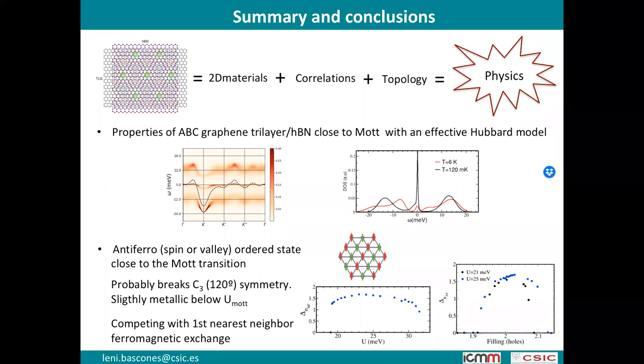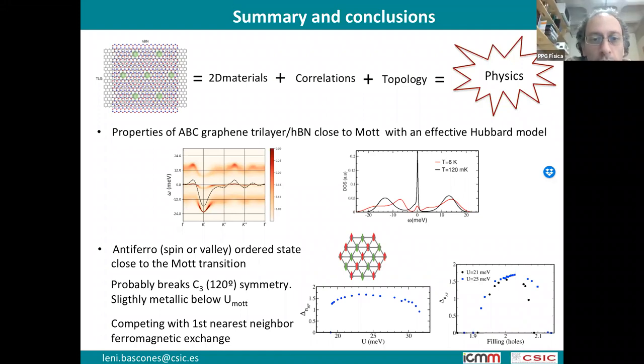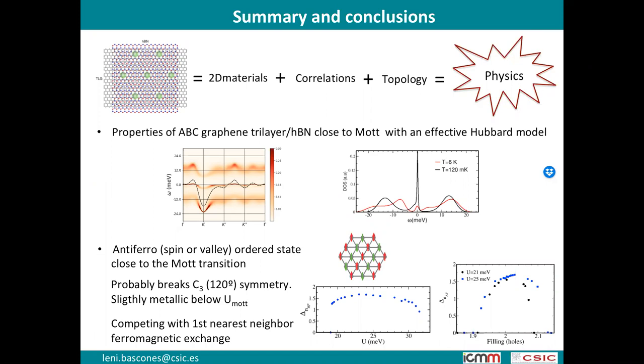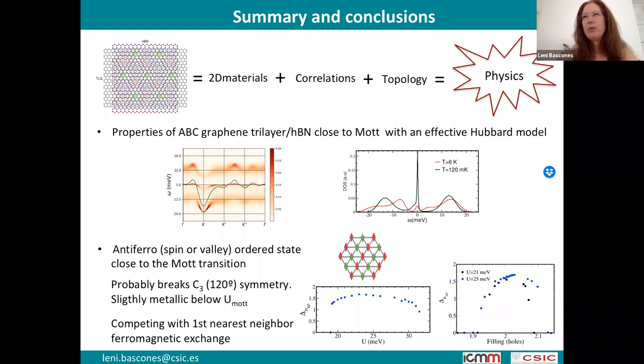My question is, can you tell us anything about the importance of phonons in all this physics, specifically the superconductivity in graphene? Are there any arguments in favor or against the importance of phonons there? So, well, there have been several issues already with phonons. First, it's not clear whether superconductivity is phonon-induced or unconventional. This is still not clear at this point. For example, superconductivity appears in many situations, and in some samples it has appeared without correlated states, in cases in which it is believed that the correlated state does not appear due to a particular screening, like the proximity to a gate.